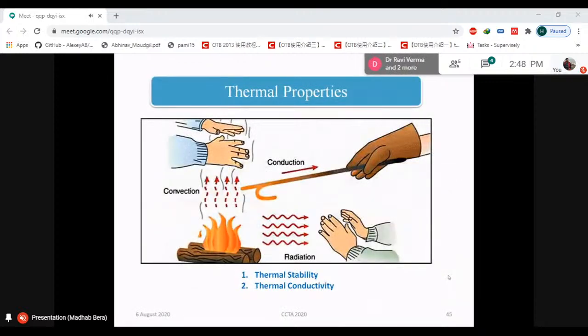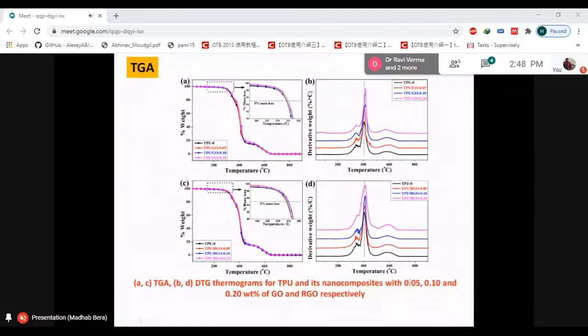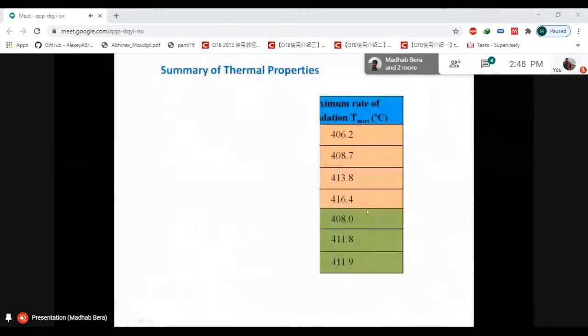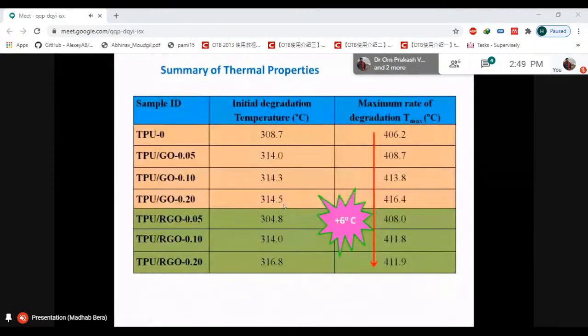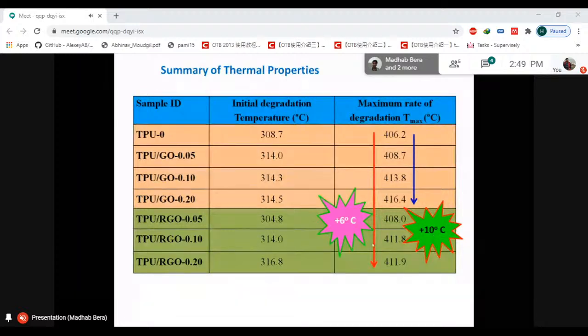Now, if we look at the thermal properties of this material, graphene-based polyurethane nanocomposite, when we talk about thermal properties, it means the thermal stability and the thermal conductivity. With the incorporation of graphene oxide and reduced graphene oxide, the thermal properties also improve. With the incorporation of only 0.2% RGO, a very ultra low loading, the stability improves by 6 degrees, but in case of GO it is 10 degrees centigrade. So this is due to the better interactions and better barrier of the material in terms of heat.